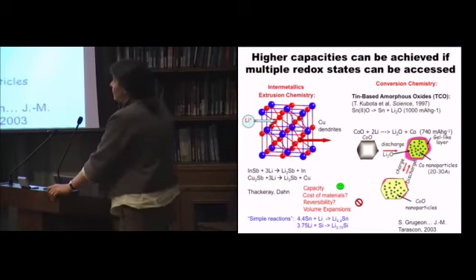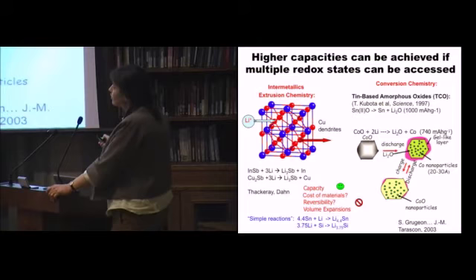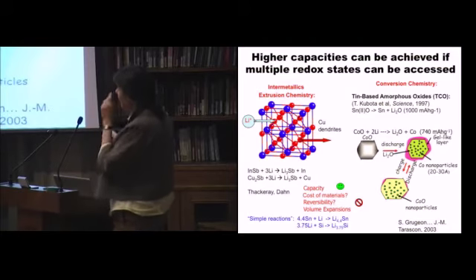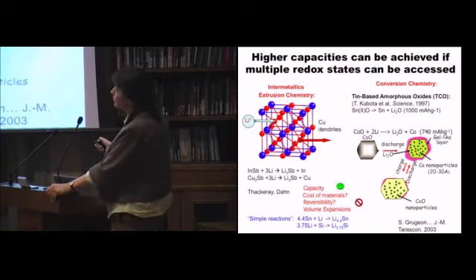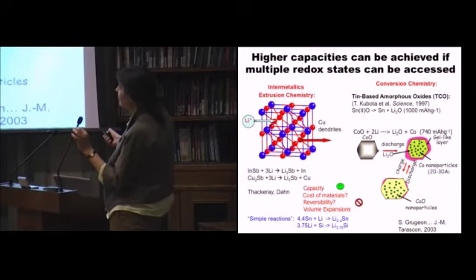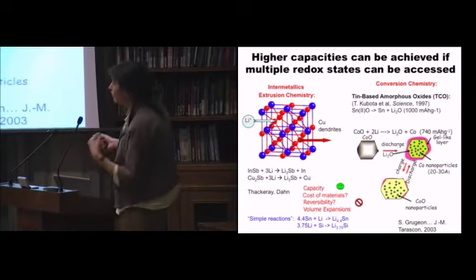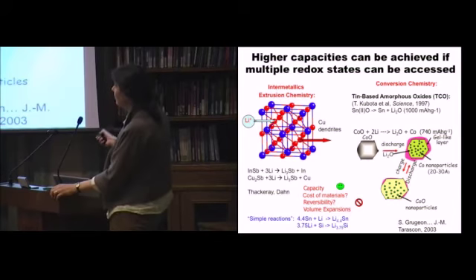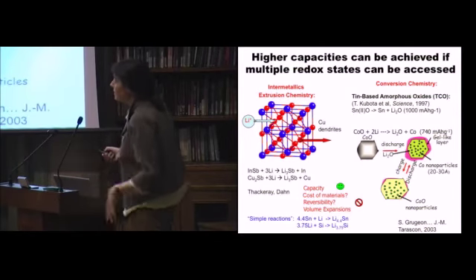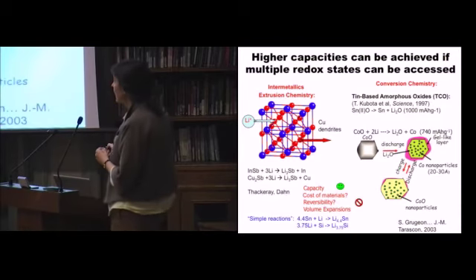One of the first ways of doing this was a so-called conversion chemistry, where Fuji Glass and then Jean-Marie Tarascon showed that you could take, for example, a cobalt oxide, react it with lithium and form cobalt nanoparticles embedded in lithium oxide. You could go backwards and forwards, cobalt 2 to cobalt 0, so double the capacity, and that could happen for many, many cycles. But the challenge is doing it with full capacity, because you've got to move electrons and ions over quite long distances.